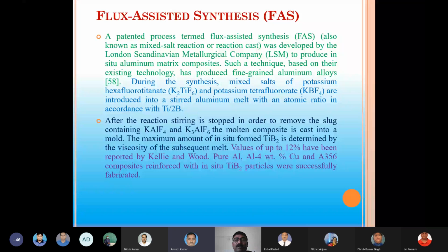Here we can use potassium tetrafluoroborate and potassium hexafluorotitanate. These halide salts are used to enhance the interface reactions, or you can say the interface bonding, between the titanium and the boron, and it will improve the properties. After the reactions, stirring is stopped in order to remove the slag containing the halide at the top from the molten composite, and it is cast into a mold.